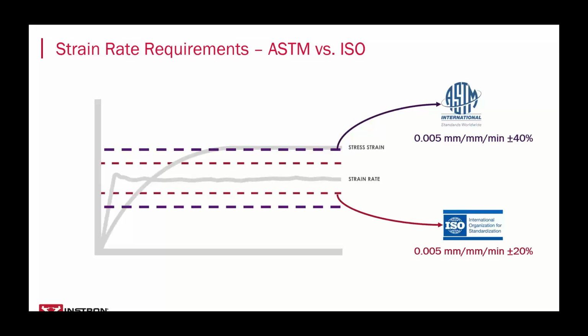This is very important to consider when you're building out your lab for high temperature testing. Of course, it's important to understand the testing requirements you have today in selecting your equipment, but if you're currently only testing to ASTM E21 today, and there's a chance that you might grow into ISO 6892-2 requirements, it's a good idea to consider how you might need to adapt if your requirements change. We'll talk more about the challenges in maintaining good strain control later in the webinar.